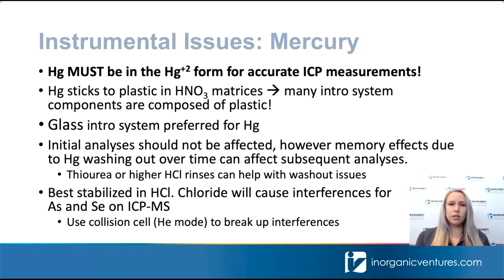Your initial analysis is not really going to be affected by this, but you are going to see washout of mercury over time. So just make sure that you are fully rinsing out your mercury before performing subsequent analyses. We recommend using a higher hydrochloric acid rinse solution to make sure you get the mercury out of your system. And we also recommend adding thiourea, as we found this is very effective in washing out mercury from the system.